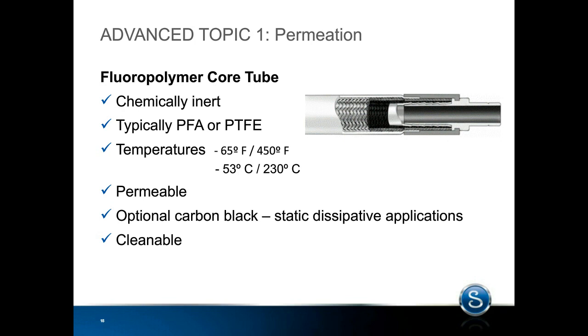And we can take this Teflon and bake it, and we call that a sintering process. And we can bake it at different lengths for different amounts of time. And what that sintering process does is tightens up the molecular structure of the Teflon. It makes the spaghetti closer together, and so it also then slows down the permeation rate. And there's two that we use at Swagelok that we call slow sintering and post sintering. Slow sintering being a slow baking process after the core tube is made, and a post sintering process is a very long bake after the core tube is made.